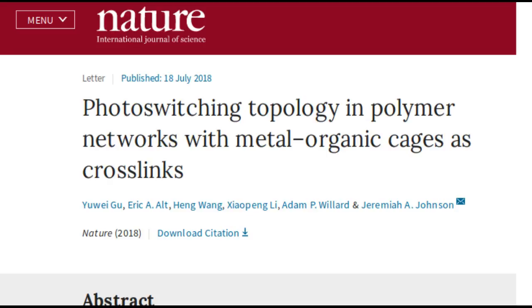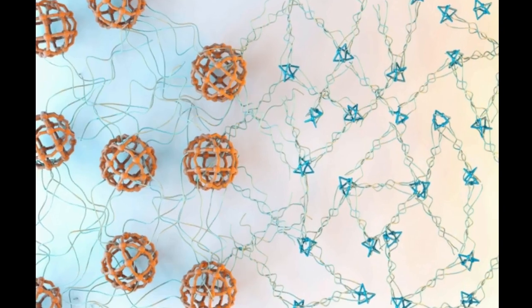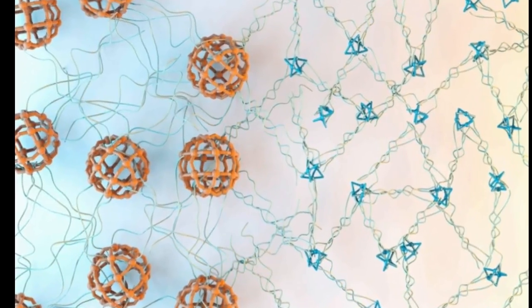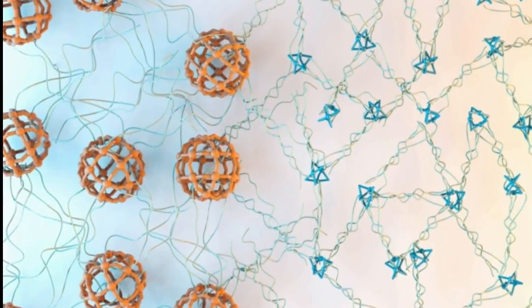The researchers created these materials by mixing polymers attached to groups called ligands, which can bind to a metal atom. Each metal atom, in this case palladium, can form bonds with 4 ligand molecules, creating rigid cage-like clusters with varying ratios of palladium to ligand molecules. Those ratios determine the size of the cages.